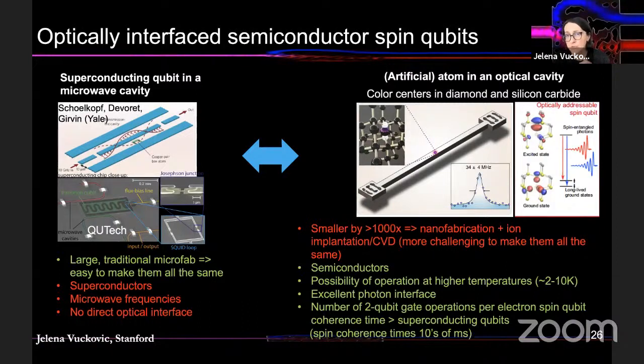And for some of these elements, also the quantum memory time or storage time is actually even better than for some of the leading platforms. So the number of 2-qubit gate operations that you can perform per spin qubit time in the material is actually even better than for superconducting qubits, because operations are very fast and the storage time is comparable in terms of the coherence time. So that's quite exciting, but of course, elements are smaller by a factor of about 1,000 relative to superconducting circuits, and you have to rely on novel nanofabrication techniques, ion implantation, growth, and so on.